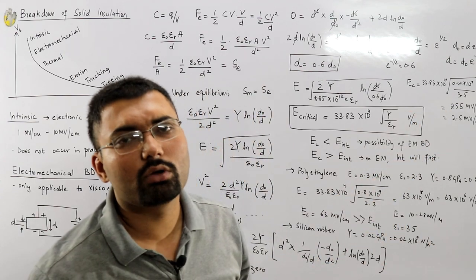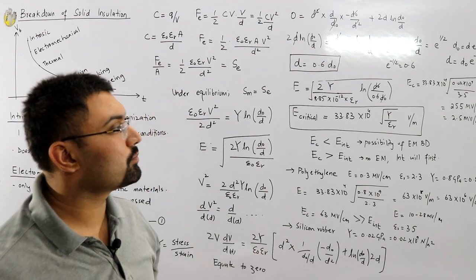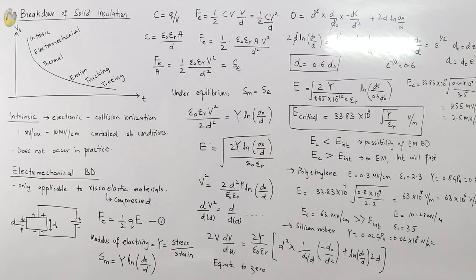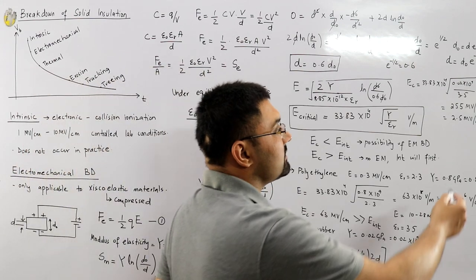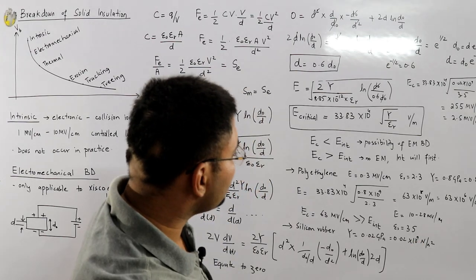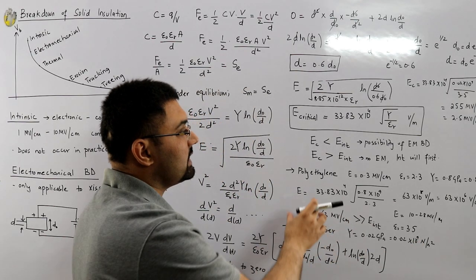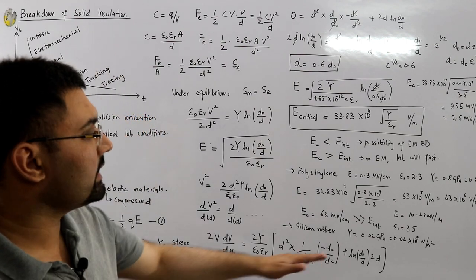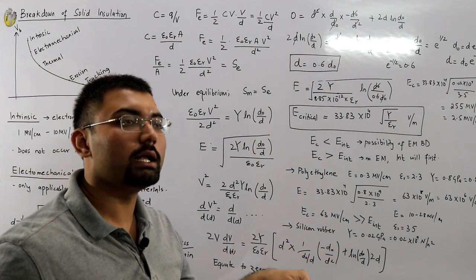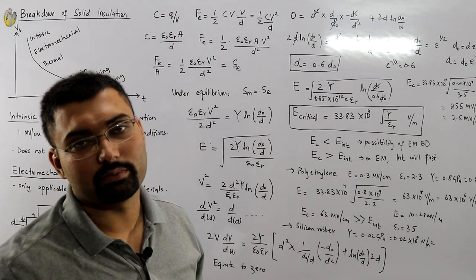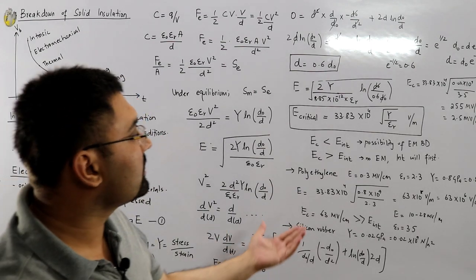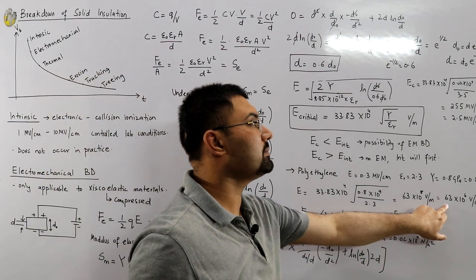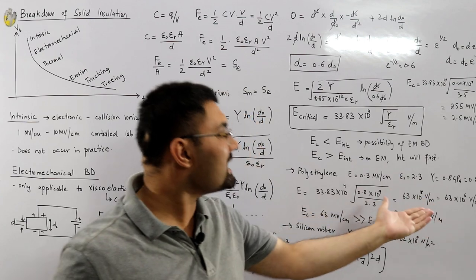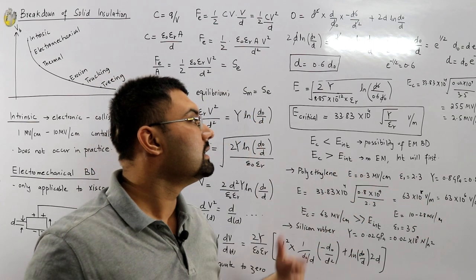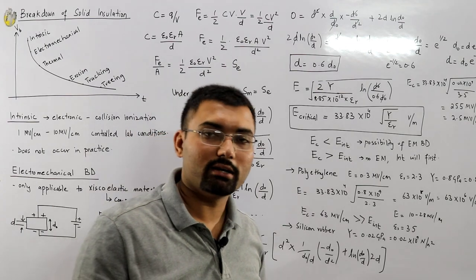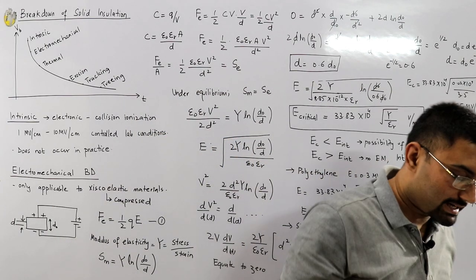Or in the worst possible case, let's say we take it 0.5. You multiply the critical field with 0.5, with that field factor or Schwager factor, and you compare with the intrinsic field and then you comment on this. Over here in the second case, silicon rubber, electromechanical breakdown is possible. But even for the polyethylene case, even if you multiply this by a factor of 0.5, still this is far greater and electromechanical is not possible, intrinsic will come first. That is what I'm trying to say.